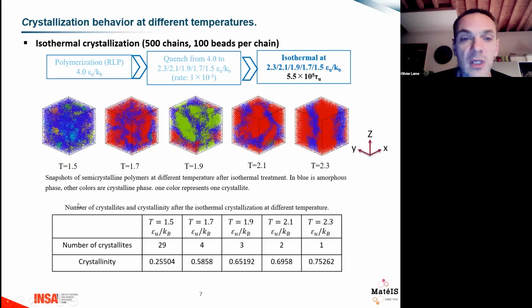Okay, so here we finally have 5 systems obtained at several temperatures. At lower temperature we have low crystallinity, a lot of small crystallites, and for the higher temperature, the lamellar system that we expected, which is what we see in reality. So these systems are satisfactory because we find what we see in reality. On this kind of system, we can be confident that we can use it to try to understand the deep origin of the mechanical properties of semicrystalline polymers. And we also have different crystallinities in relation to the isothermal temperature.